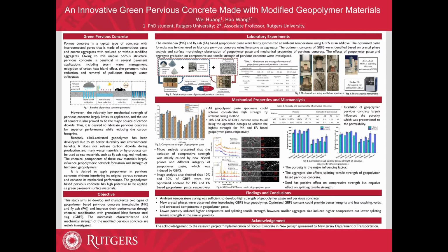Combining this result, we can finally determine the formula, and we use this formula to prepare the geopolymer-based pervious concrete. And we did the porosity test and the permeability test on the porous concrete. The results are shown in Table 2. We can find the specimens with gradation A1 have the highest porosity and also the highest permeability. And also the correlation between the porosity and the permeability is linear.